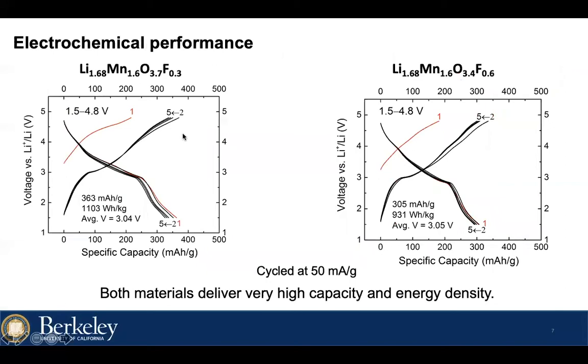After testing the electrochemical performance, we found both of them deliver very high capacity and energy density. They were cycled under 50 milliampere per gram current density. For the first compound with lower fluorination level, the initial capacity is higher than 360 milliampere hour per gram, and the corresponding energy density is higher than 1100 watt hour per kilogram.